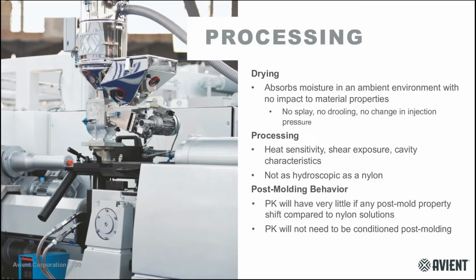Now going on to the latter part of that, okay, now the parts have been molded. What do I need to do post-molding to be able to keep this part where I want to keep it in terms of dimensional stability? Polyketone will have very little shift in properties when you compare it to nylons. That's the known fact and known Achilles heel of nylons, is that the material will tend to shift post-molding, and that's why you see dry as molded versus conditioned settings on a data sheet with nylon. With polyketone, that is not the case.